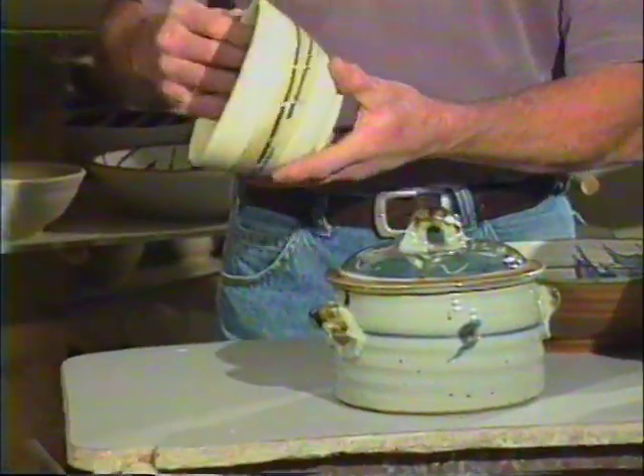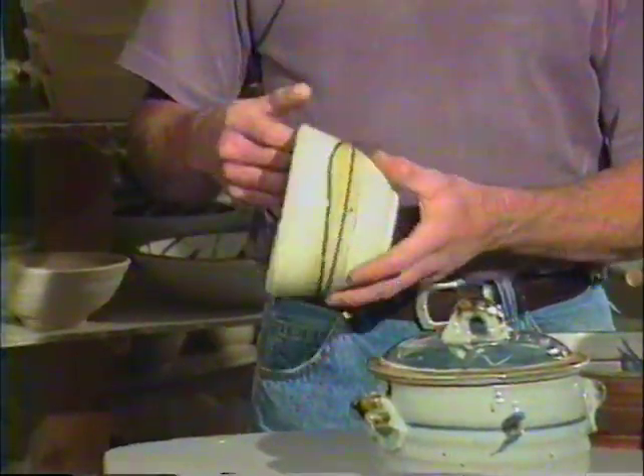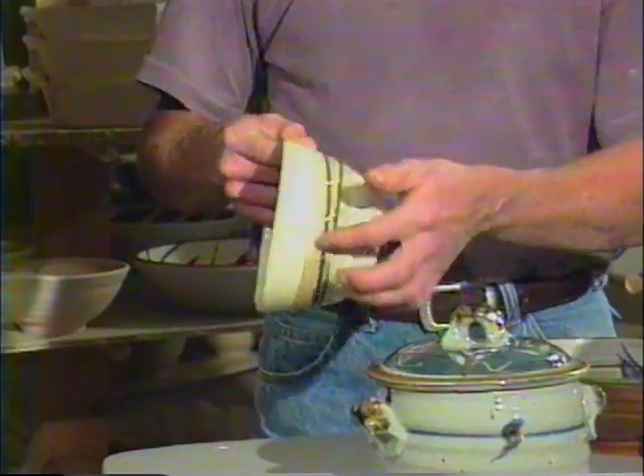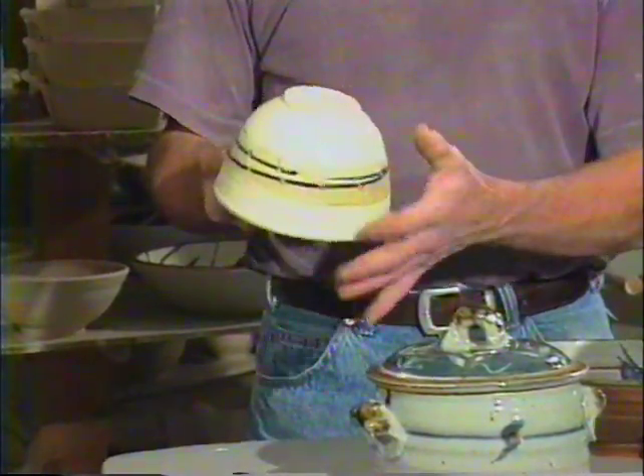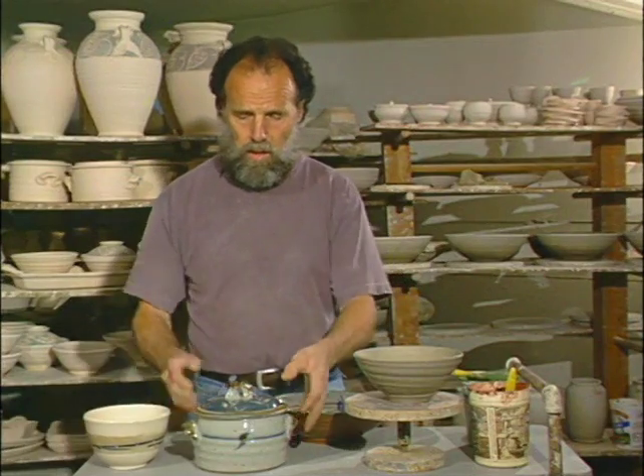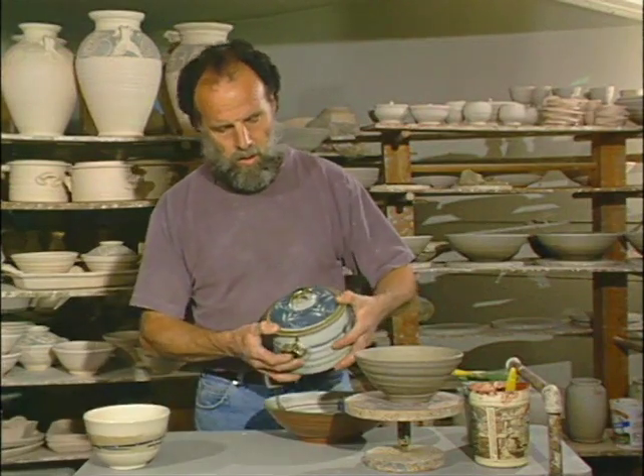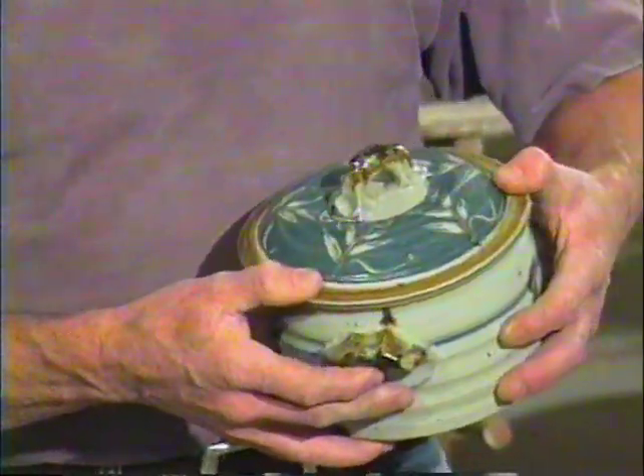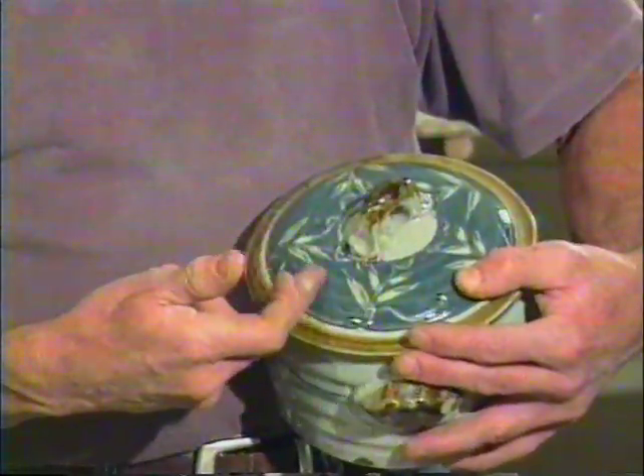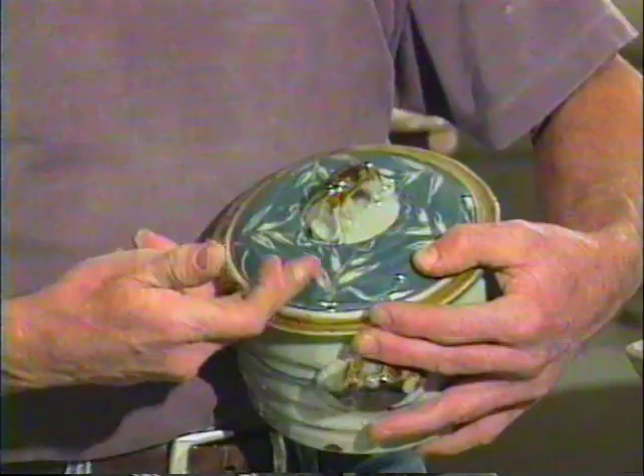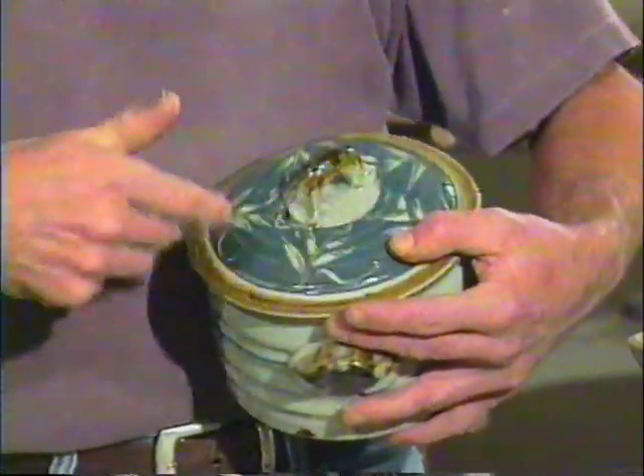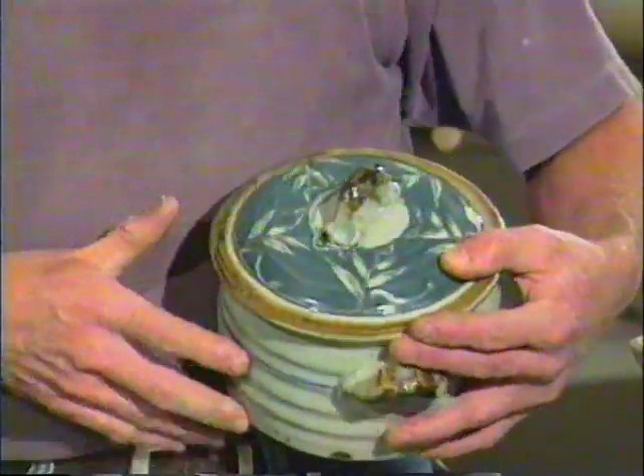Here we have a mid-fired pot with a similar thing. We've got a light brown slip underneath and then a blue trailed over and a transparent glaze over the whole thing. And here with this high-fired pot, again, similarly treated. Got a blue slip underneath, some excision from it, some colouring oxides perhaps over the top, and then the whole thing wreathed in a transparent glaze.